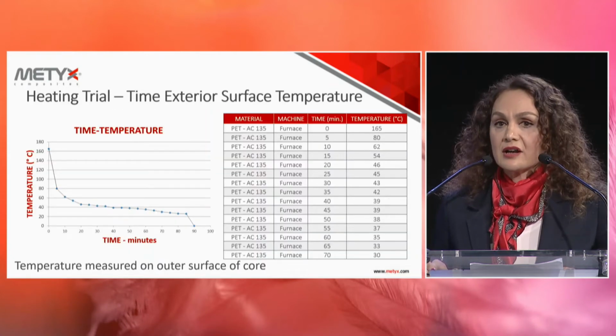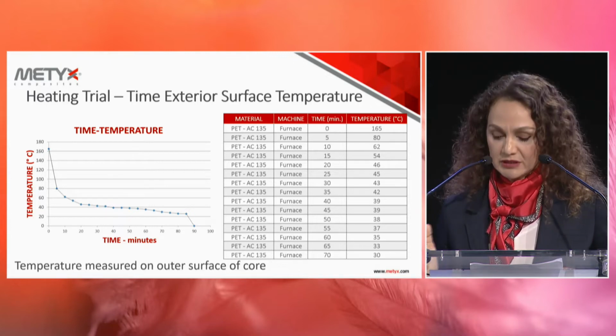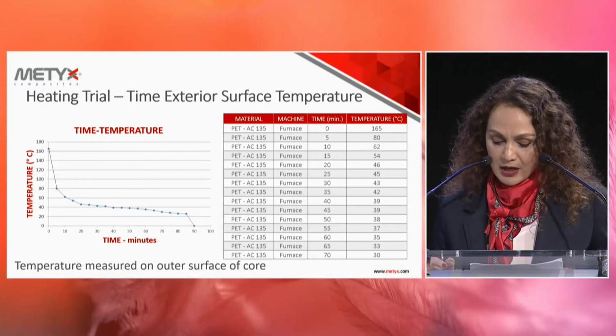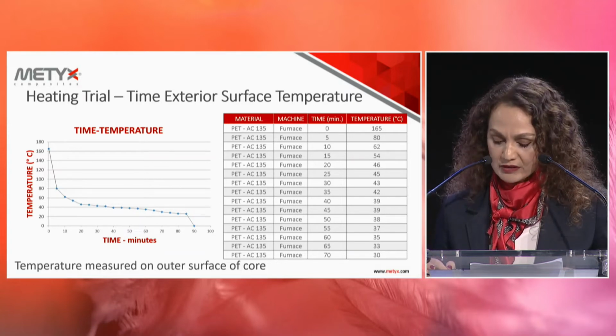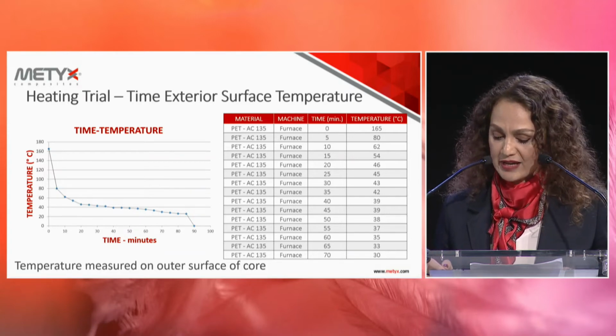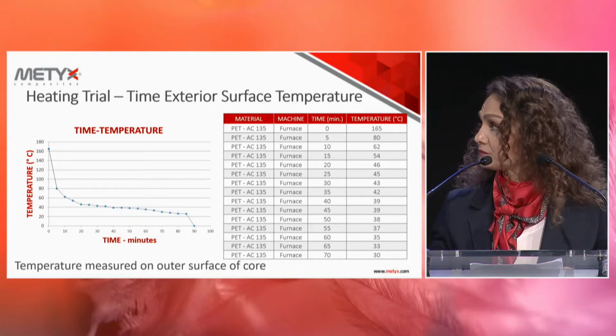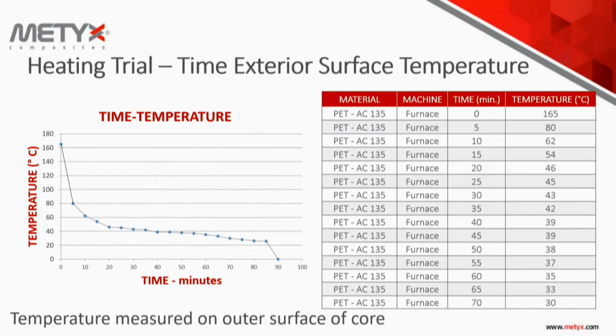In order to understand how much time we need to form the foam when we take it from the oven and put it back into the mold to form it, what is the retaining time to shape it? Here on the graphic, you see almost a 50% drop in temperature in 5 minutes. So the graph shows that if you want to form the core, we have about 5 minutes to get it from the oven, put it under the bag, and pull the vacuum before it starts to lose its thermoforming properties.